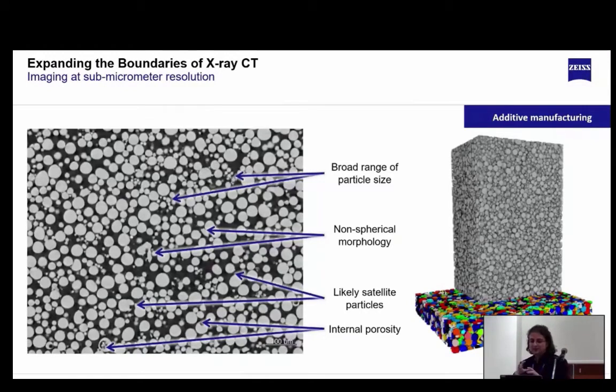They might come in a broad range of particle sizes, which can be a problem for melting purposes. In fact, there are some particles that already contain porosity, as you can see at the bottom. And this can degenerate into an explosion during the build and create some kind of cracks in the process of generating the part.